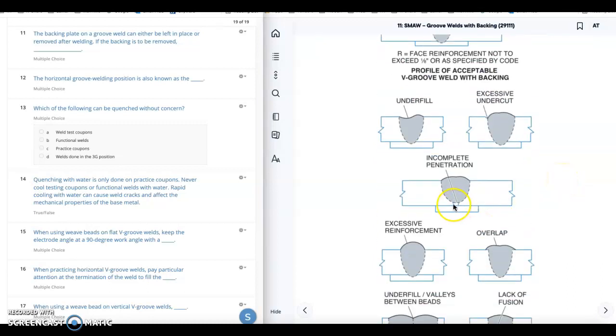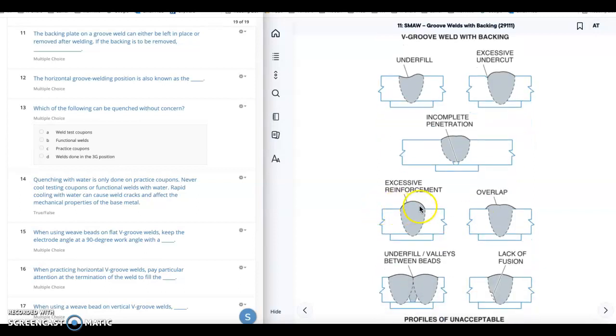Incomplete penetration. That would show up on the X-ray as incomplete penetration. The root weld did not have 100% penetration down to the backing strip. Excessive reinforcement. This big hump right here on top.